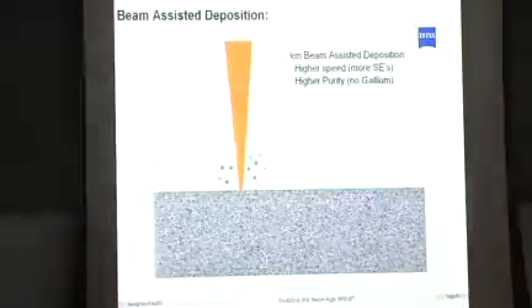One of these institutions started doing lithography, and they're getting very nice small probe sizes or small pillar sizes. Some of them you can see knocked over here. I showed you just so you can get the aspect ratio of these. There's much less proximity effect. Again, imagine the helium beam entering the sample. It stays collimated as it goes through, and it doesn't backscatter a lot. So a lot of those things limit the performance of an electron beam. We have no trouble keeping it focused as it enters the sample.